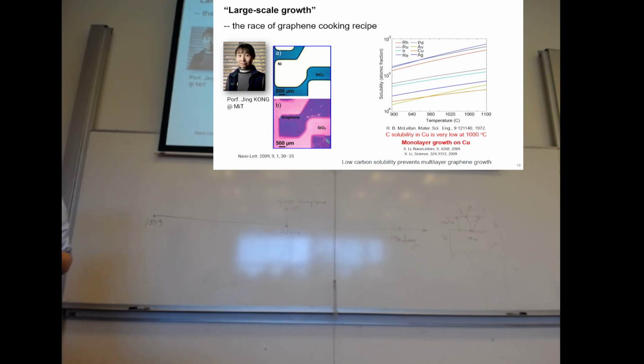What she did was grow CVD graphene on top of a nickel surface. And then you can see that there is a homogeneous graphene layer, a few layers, covering everywhere there is nickel. When there is silicon oxide, there is no graphene. When there is nickel, there is graphene. Because at that time, graphene growth needed a catalyst. The carbon precursors come into this very hot chamber, and they can be decomposed, forming adatoms everywhere. But on the surface, you need the help of a catalytic surface to really form a layer of graphene. So graphene can only form on top of nickel, not on silicon oxide.